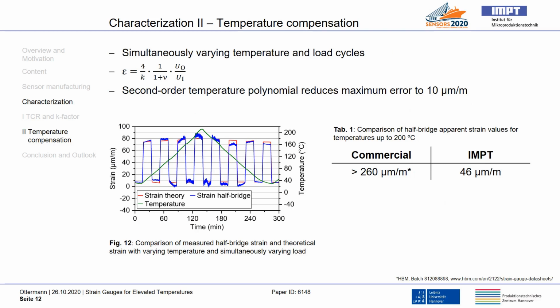Next, the characterization is shown regarding the temperature compensation capability for half bridges. Therefore, varying temperature and load cycles are applied at the same time. The measured strain, according to this formula, consists of the K-factor, the Poisson's ratio, the input voltage and the output bridge voltage. The result is shown in table 1. The maximum error of 46 micrometer per meter is at least factor 5 lower than the value of commercial strain gauges, which are in a half bridge configuration.